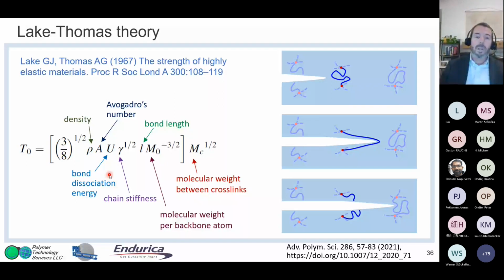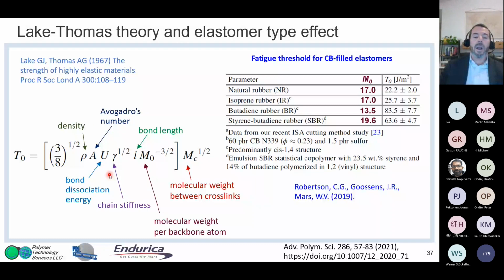And what you can see is that if you hold everything constant and you change only the elastomer type, the main area where things are going to change is this M0, molecular weight per backbone atom. Smaller is better. Notice the minus sign here. And chain stiffness has a positive impact on fatigue threshold.